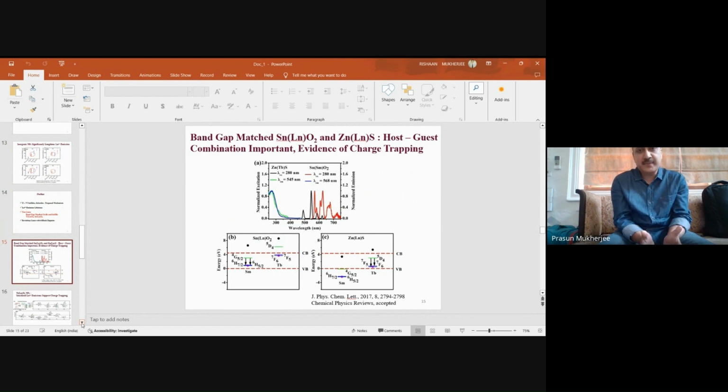As the band gaps are similar, or nearly the same, if a spectral overlap mediated model were operating, one should expect similar sensitization efficiency. Experimentally, however, we saw that sensitization is only present in SnO2:Sm and ZnS:Tb, and the other two systems, SnO2:Tb and ZnS:Sm, did not show any sensitized lanthanide emission. That correlates perfectly with the corresponding energy level diagrams and the charge trapping model.